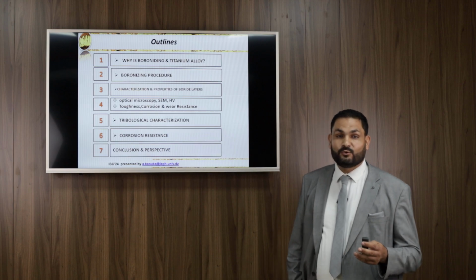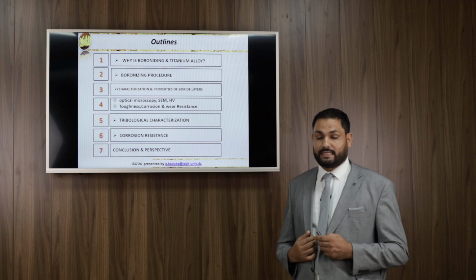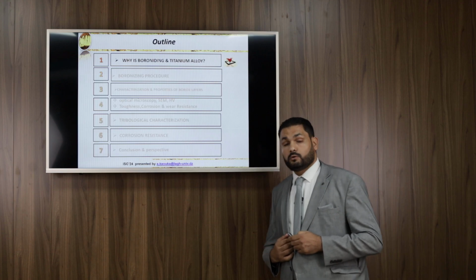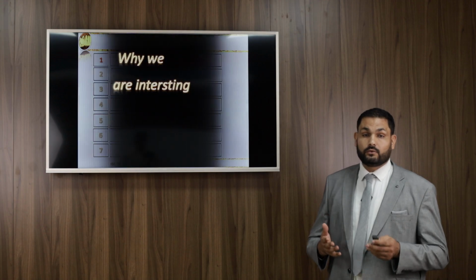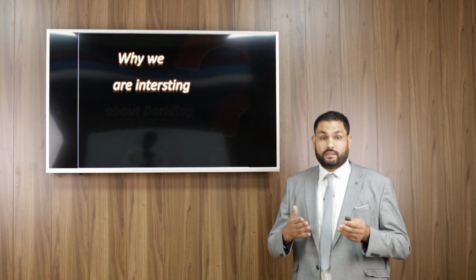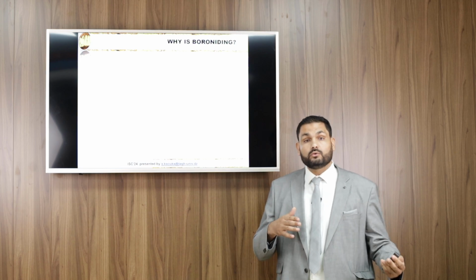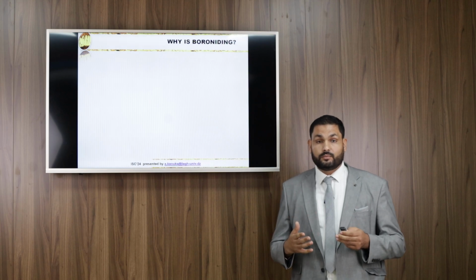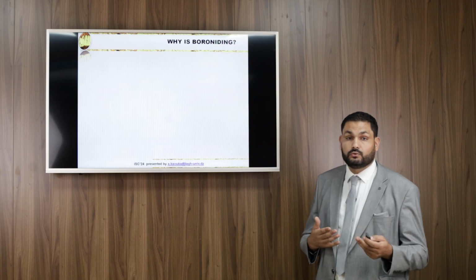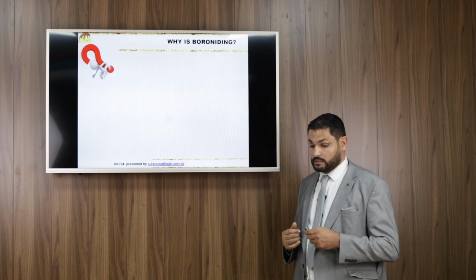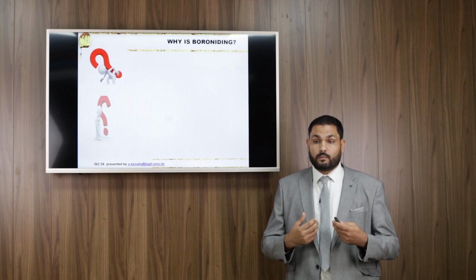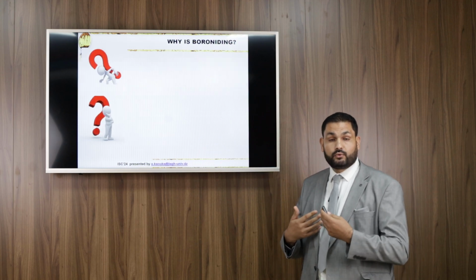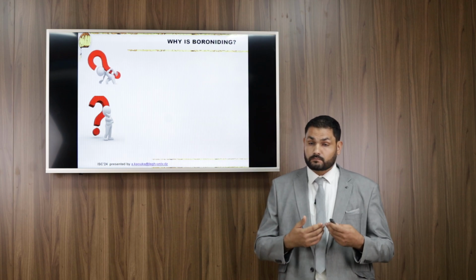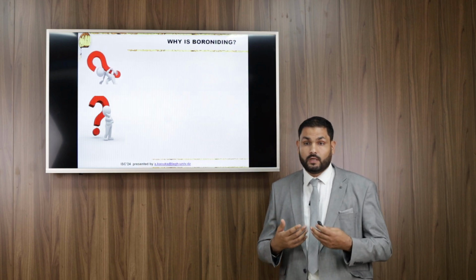So maybe you are asking the question, why are you interested in boriding? Boriding, also called boronizing, as you know, is a thermochemical surface treatment in which boron diffuses into the surface of the treated part at high temperature, ranging between 800 to 1000 degrees Celsius, for a few hours, between 2 to 8 hours. And due to its good properties, it improves the mechanical properties of the substrate.